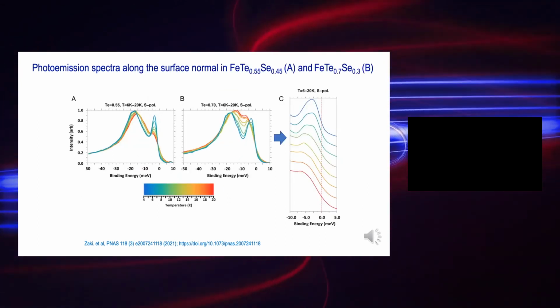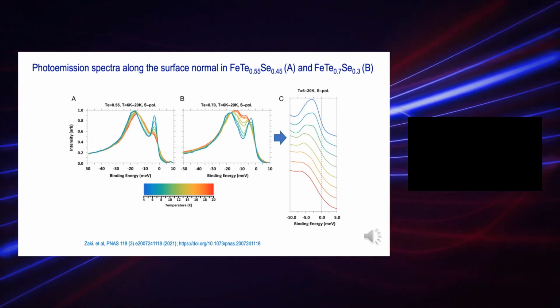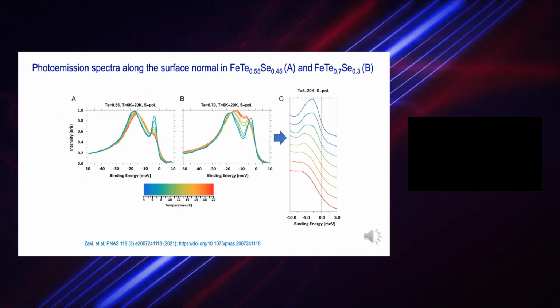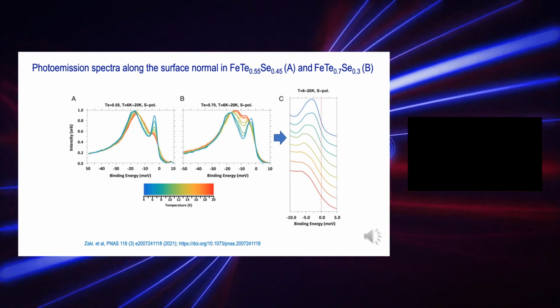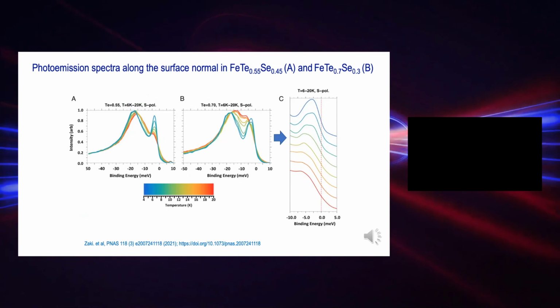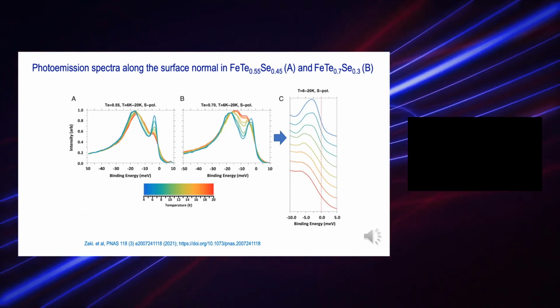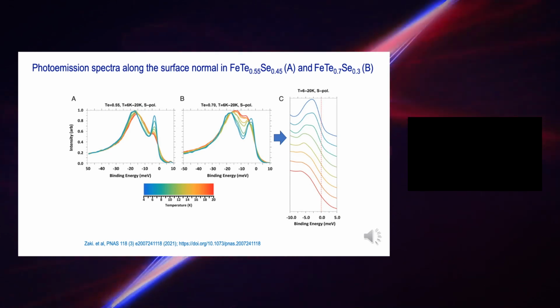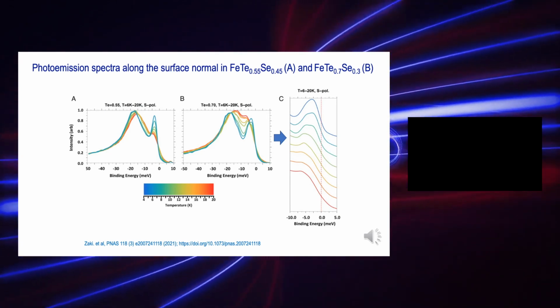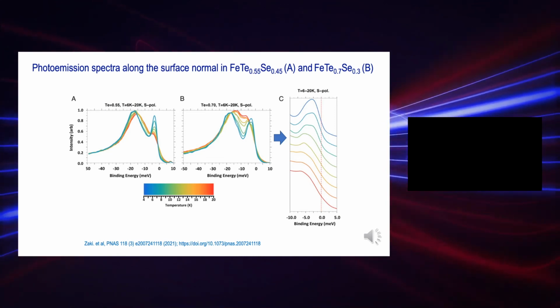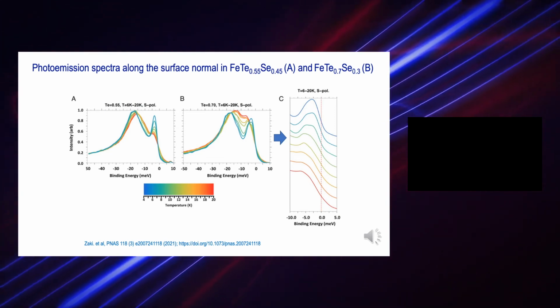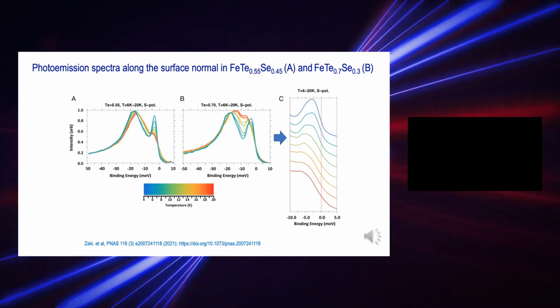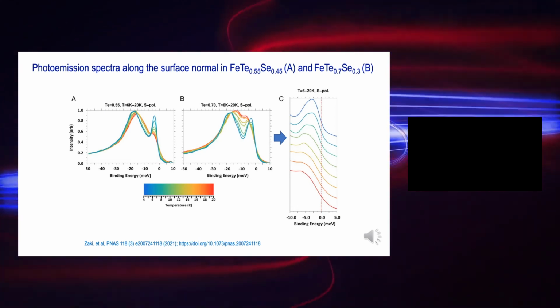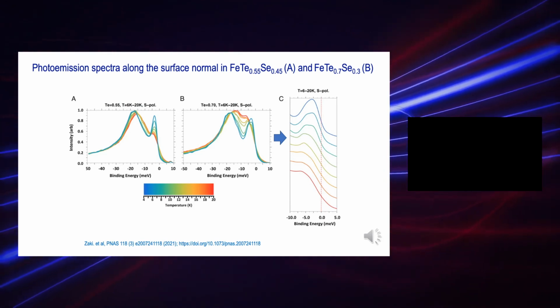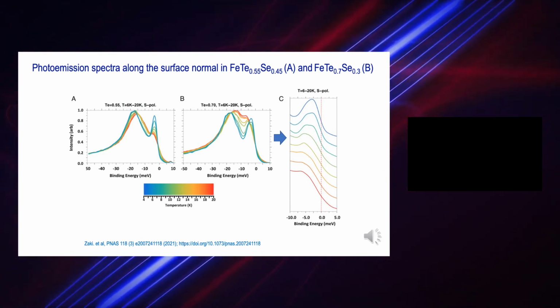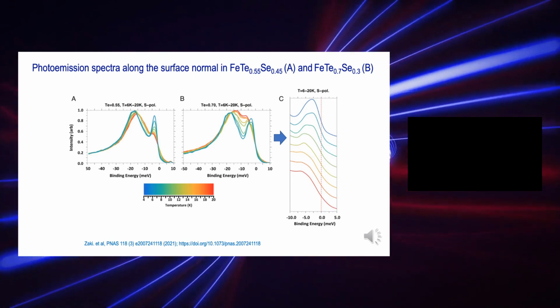The spectra here are taken along the normal direction in iron tellurium selenium. Of two samples, A has a lower tellurium concentration and B has a higher tellurium concentration. At 20 Kelvin, increasing the tellurium concentration from 0.55 to 0.7 results in an increase in the intensity of the peak. And the vicinity of the Dirac point clearly shows the data is related to the tellurium concentration. It signals that a stronger spin orbital coupling is realized in sample B.